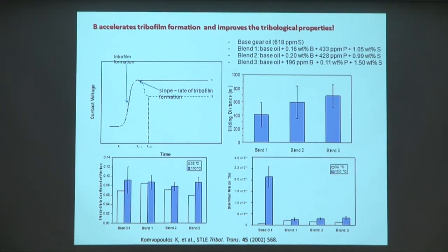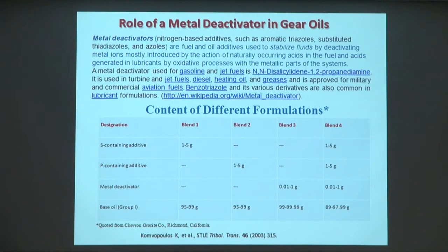So when we reach a critical stage of activation, we have the chemical reactions taking place and the film is forming and reaching a steady state or slightly dropping, but reaching a steady state that is non-zero. And so we can see here that the sliding distance for these three blends increases, but the most important is the wear coefficient for the base oil and the two blends at these two temperatures, how much has been reduced by these additions of boron and reduced sulfur.